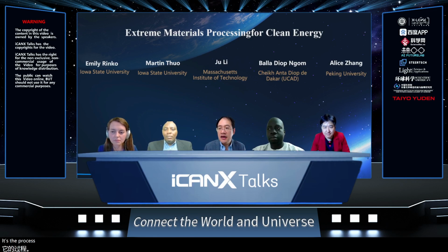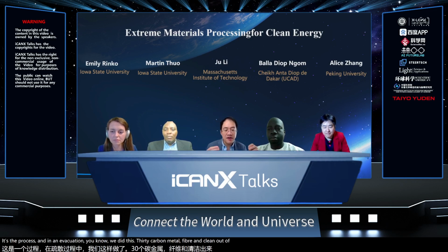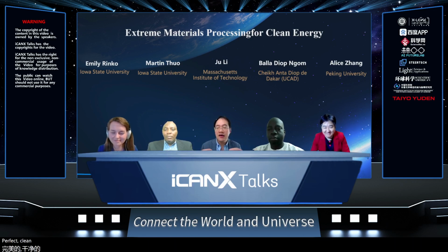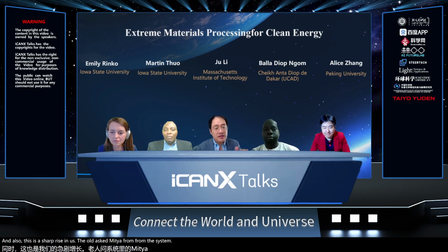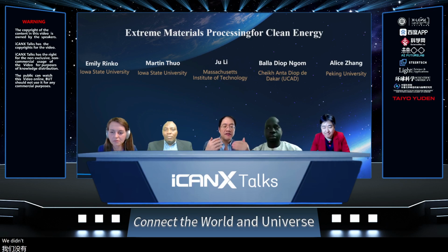process. In that case, we did this dirty carbon nanofiber and the clean nanofiber. It's relative, even though we call it clean, it's not perfectly clean. We see the dirty fiber gives much smaller nanoparticles, more uniformly dispersed, and also a sharp rise in the CO emitted from the system. In that experiment in 2018, we didn't give it oxygen gas because this carbon fiber has oxygen on the surface to begin with.